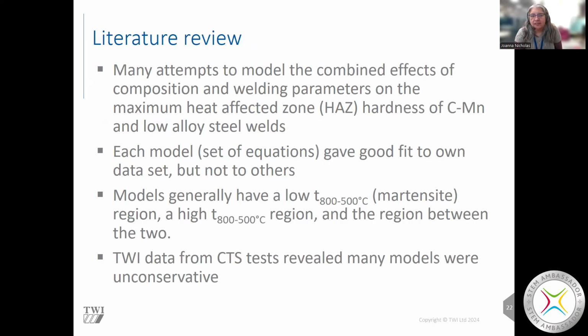So how did we do it? Started off with a literature review, looking at lots of different places where the thermal cycle or weld data was reported alongside the hardness data. There have been a number of attempts to model the combined effects of composition and welding parameters, and there were lots of different models that existed. Every model gave a good fit to its own data set, but not necessarily to others.